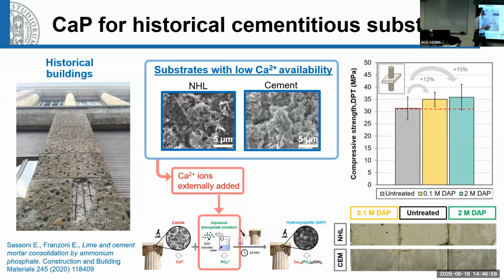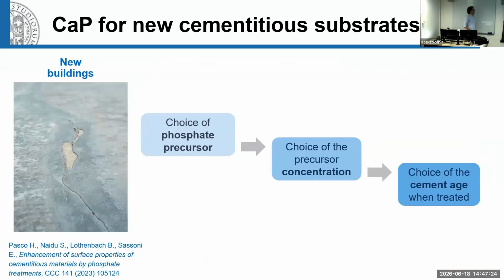So also in the case of cement, what we found was some improvement in mechanical properties, for instance in terms of compressive strength, but then we tested also many others, without any significant color change. So also in the case of historical cement, it's possible to use the same technique to improve mechanical properties. Then we also investigated the possibility of using more or less the same technology in the case of new cement.